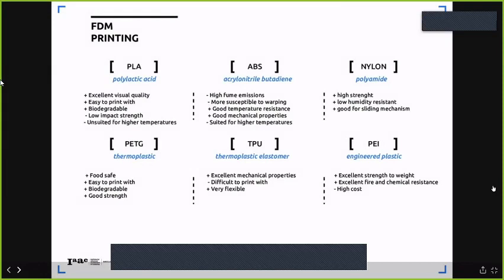So we have nylon, a standard, really high technical plastic, really nice, really annoying to print on the other hand, but you get really strong and performant parts. Why? Nylon is a hygroscopic material. That means it grabs all the humidity of the air. And when plastic grabs humidity, what happens when you heat up water? It boils, no? And produces steam. Imagine this on a really small scale. The plastic that you are melting, if it has too much water content because it's hygroscopic, will create steam inside the plastic and produce small bubbles, reducing your print quality.